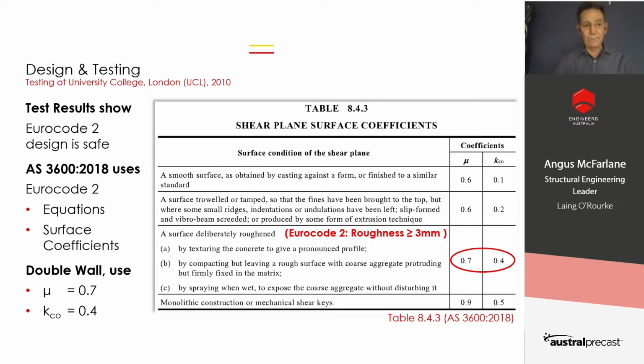But for double wall, we use these parameters, which are very good. Those are the second highest parameters you can get. If you look down the bottom here where my cursor is, the highest parameters are for monolithic construction, which is 0.9 and 0.5, versus 0.7 and 0.4 for double wall. So we get very nearly completely composite construction.